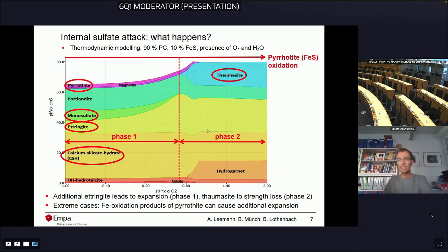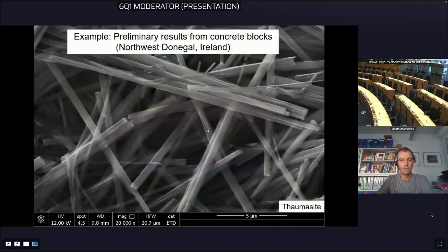Now, how does this look in reality? And for that, I would like to jump to the samples I got from Paul Dunlop, 4 samples in total. Next slide, please. You see this very nice mineral here. This is thaumasite, and look at the scale at the bottom, so 5 micrometers. A thaumasite needle is probably about 1 micrometer across, so a human hair is about 60 micrometers. So you see this is a really fine needle. Okay, now this image was done with a scanning electron microscope, and now let's move one further.